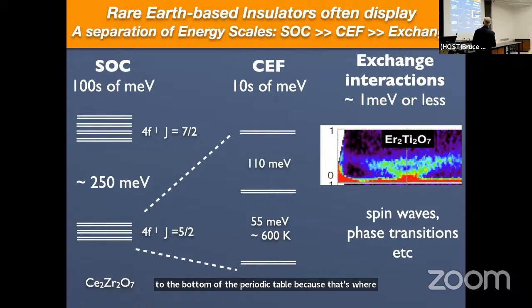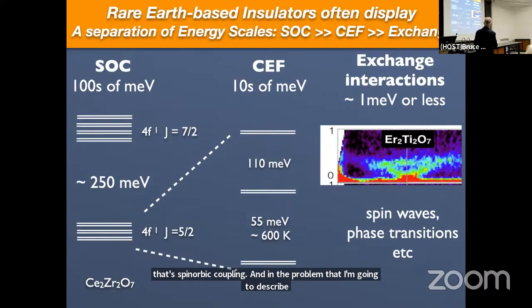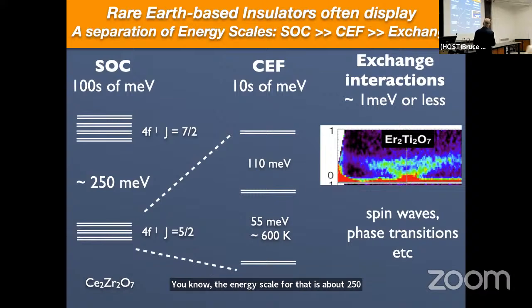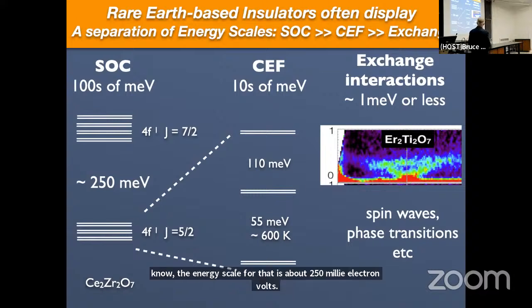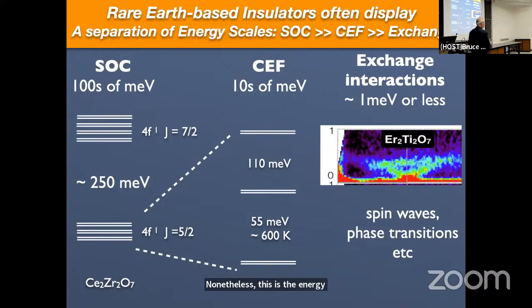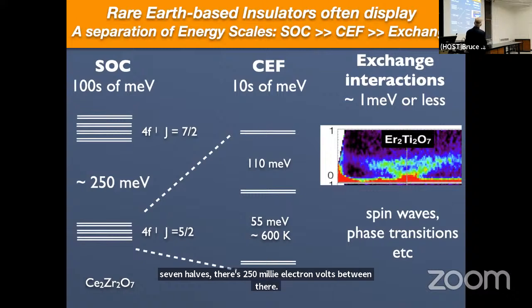So that's spin-orbit coupling, and in the problem that I'm going to describe, the energy scale for that is about 250 millielectron volts, okay? Nonetheless, this is the energy scale that separates the Hund's rule ground state, which is J equals 5/2, from the next excited Hund's rule state, which is J equals 7/2. There's 250 millielectron volts between there, okay? Then the next effect will be what are referred to as crystal field effects, okay?